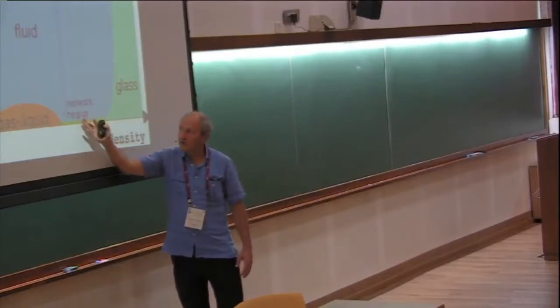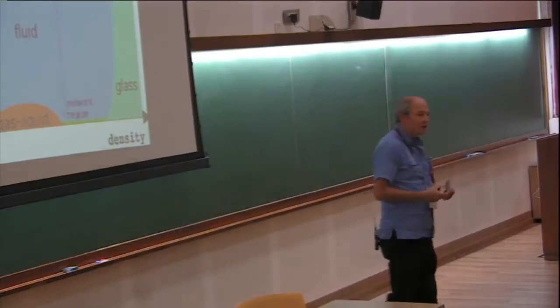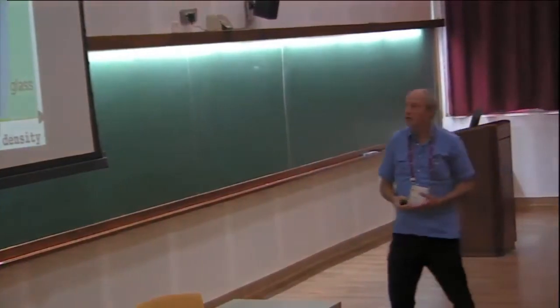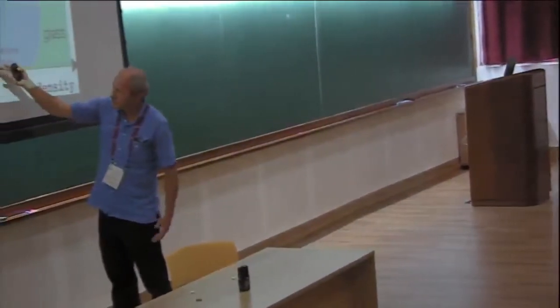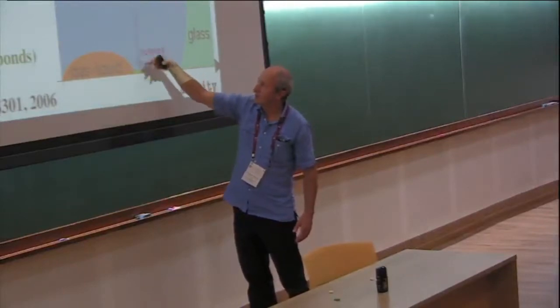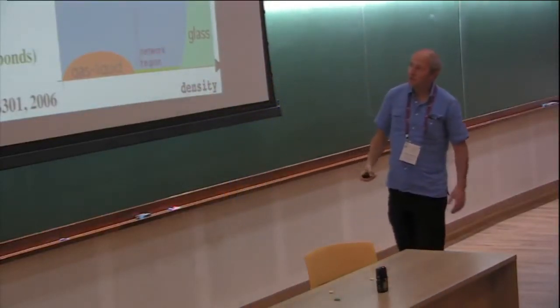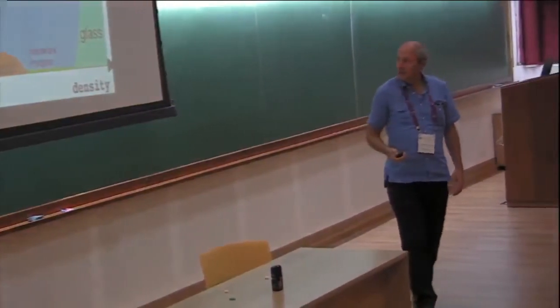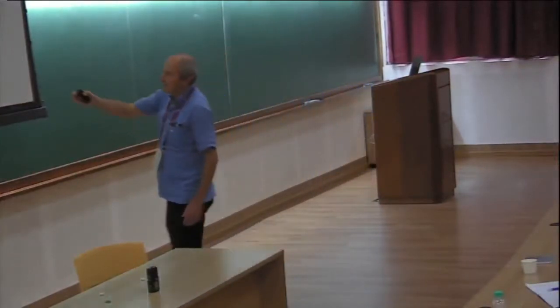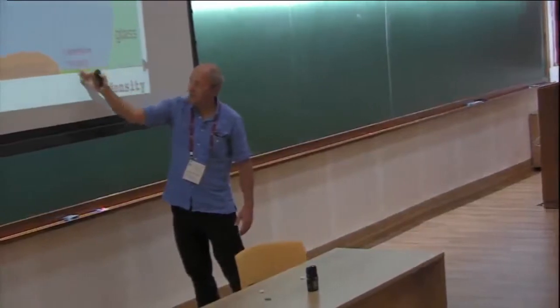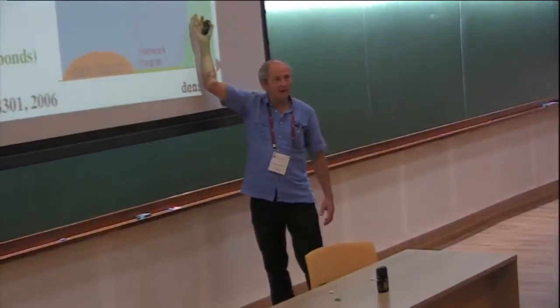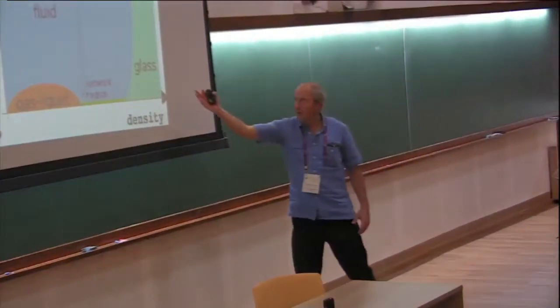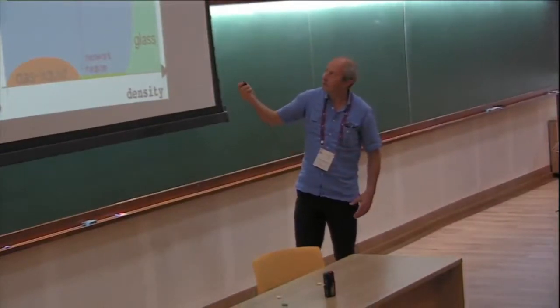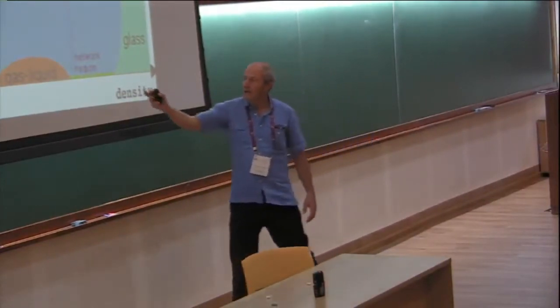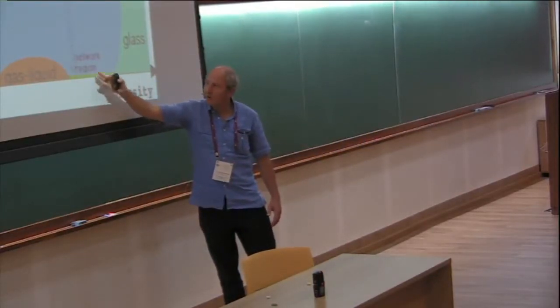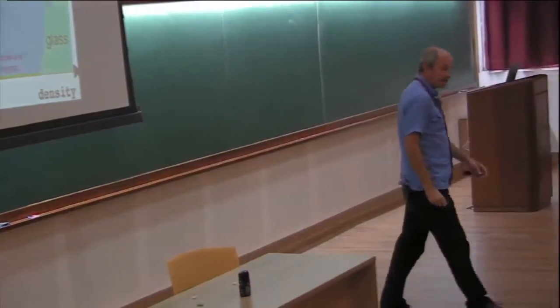And in this region here, I'm trying to convince you that what you have is a liquid which is essentially a network controlled by the bonds and by the lifetime of those bonds, which you can control with temperature. So if you go to very low temperatures, you're going to have very long-lived bonds and a very stable network, and if you raise the temperature, then you start to break those bonds more quickly, more frequently, and you have a system which is more typically liquid-like. So this is a dynamical arrest, which I like to call of the gel type, that you see here, which is conceptually different from the one that you have discussed this week due to the excluded volume, which is the typical one of a glass of spheres. In some sense, this is why hard spheres are so important, because they are really the model for packing, and this kind of limited-valence model is the model for networks. So there are two extreme classes of materials that we can have.